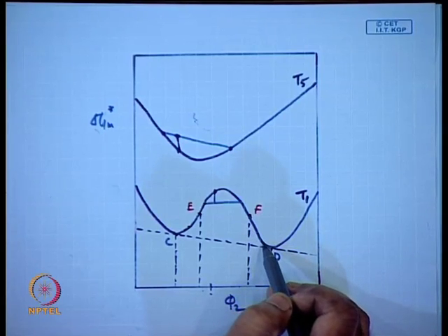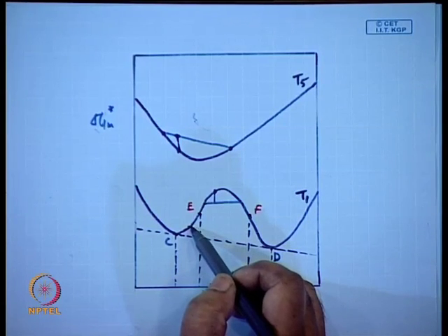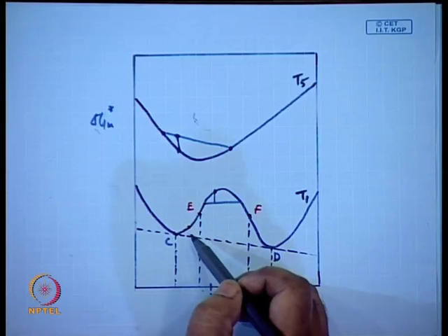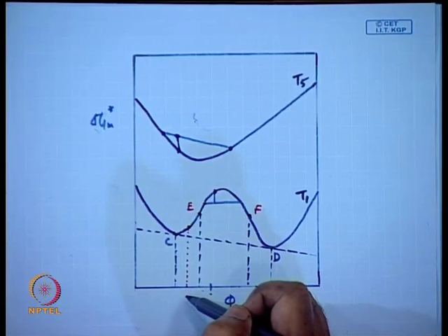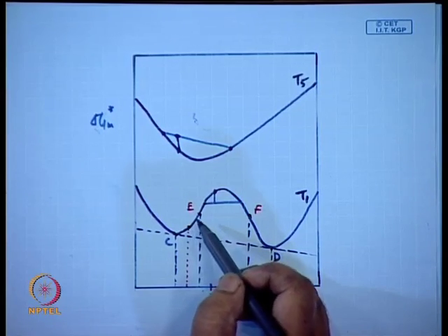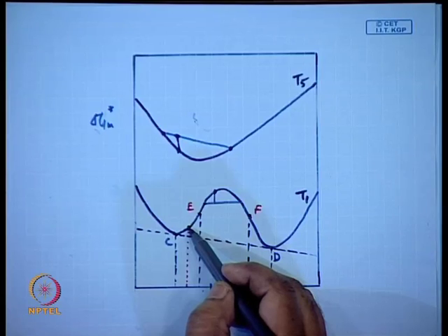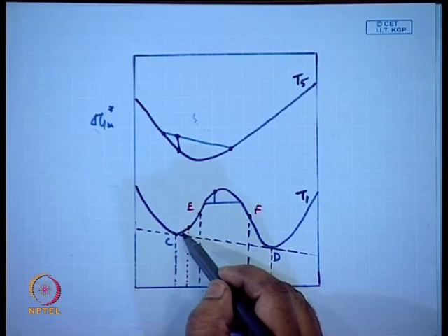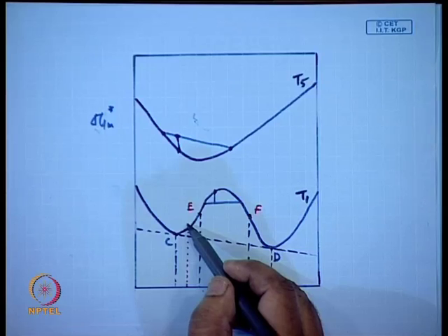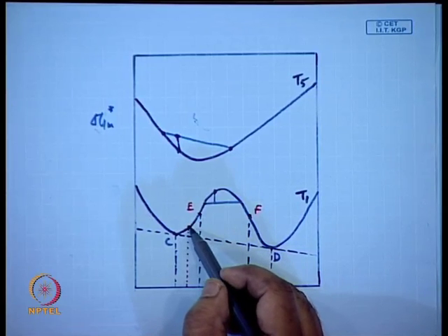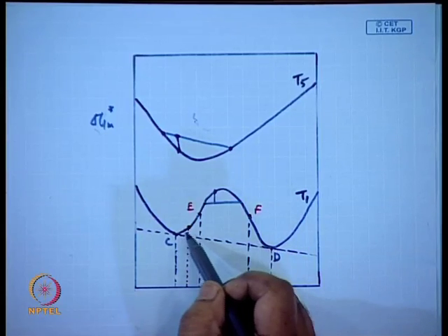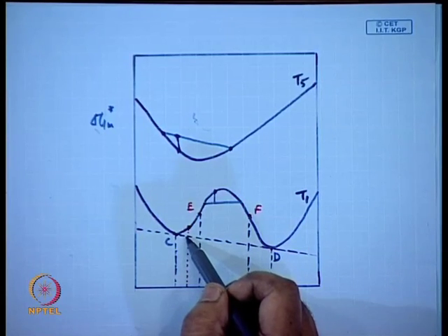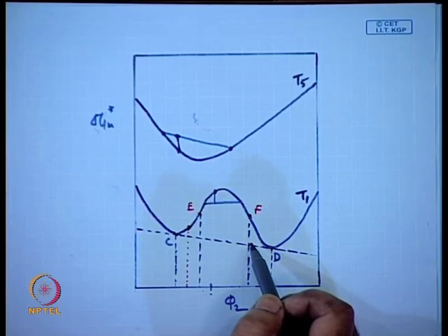Similar, same in this case, but if this has to phase separate, if I consider this point which has this value of phi 2, if this has to phase separate into two phases having composition between this point and this point, then obviously delta G mixing would be positive. So, that will be unfavorable, but if this composition phase separates into a point here and here, the delta G would be negative. So, it will spontaneously phase separate.